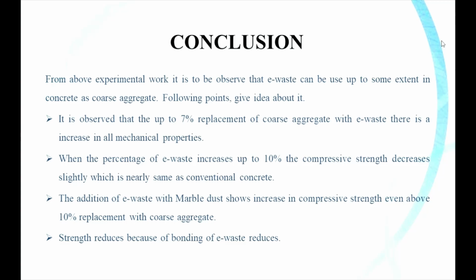It is observed that up to 7% replacement of coarse aggregate with e-waste there is an increase in all mechanical properties. Tables are the proof which show that up to 7% replacement of coarse aggregate there is an increase of strength. After 7% there is a slight decrease of strength. Second, when the percentage of e-waste increases up to 10%, the compressive strength decreases slightly, which is nearly the same as the conventional concrete.